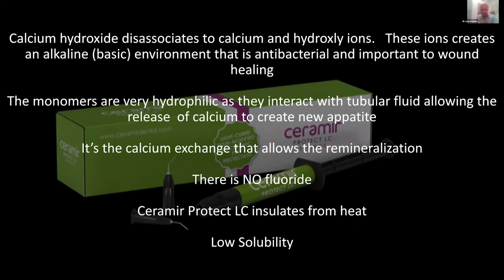You have to understand that calcium hydroxide dissociates into calcium and hydroxyl ions. The hydroxyl ions are alkaline, and this is essential for what I would call bioactivity. This alkaline nature is antibacterial and leads to wound healing. So calcium hydroxide breaks down to calcium and hydroxyl ions. The monomers are very, very hydrophilic, and as they enter the tubular fluid, they will release calcium to create new apatite.